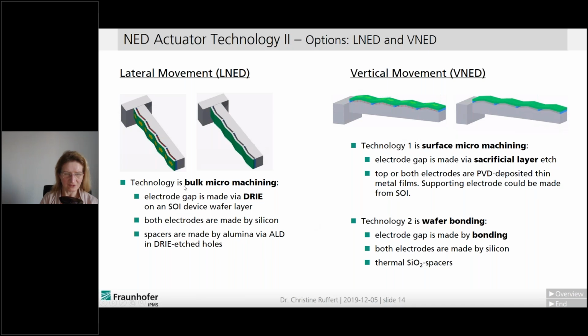The corresponding technologies are as follows. On the left-hand side, for the LNED, we are using bulk micromachining, which means the system is fabricated predominantly by deep reactive ion etching, also known as the Bosch process, which is used for patterning silicon with very, very deep trenches. Both electrodes are made of silicon in this case, and the spacers are made of alumina, which is deposited by atomic layer deposition in the holes that have been created by deep reactive ion etching before. For the VNED, there are two alternatives possible.